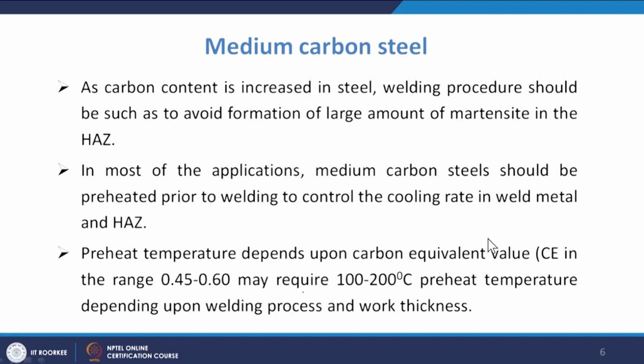How can we reduce it? One is providing the preheat treatment and slower cooling rate, and to reduce the stresses we can do the post weld heat treatment. Okay, in most applications medium carbon steel should be preheated prior to welding to control the cooling rate in the weld metal and HAZ. Preheat treatment depends on the carbon equivalent value, that is ranging from 0.45 to 0.6 percent, and may require a preheating temperature of 100 to 200 degrees depending on the welding process and work thickness.